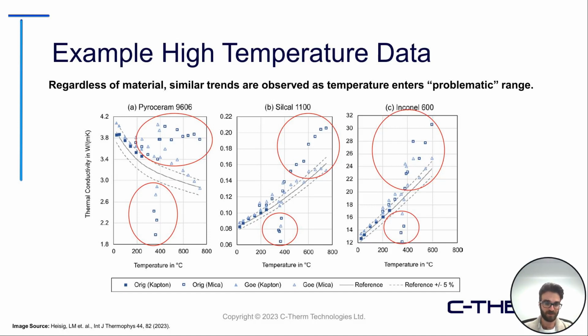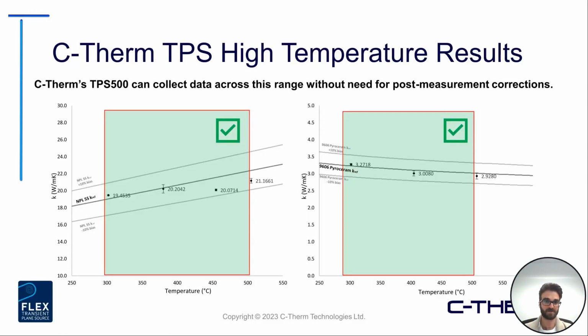So really, again, above 300 to 500 C, that error really starts to increase. So this is obviously a problem, and it's one that we've actually addressed here at C-Therm for our high temperature sensor line, the TPS 500. This is just some example data that was collected on some reference materials, but you can see an NPL stainless steel and a standard pyroceram reported here, and just really zeroing in on the problematic range that's been observed by many groups.